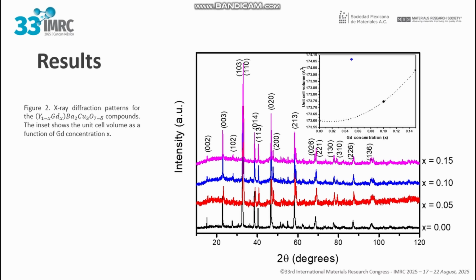These are the results we got. First, these are the diffraction patterns for all the compounds and concentrations. As you can see here, the compounds did not show too many chemical impurities. We got pretty much the phase that we wanted to get. And in the inset, you can see that the unit cell volume actually grew with the increase of gadolinium content in its structure, with the exception of 0.05. This volume was calculated using the cell parameters found by doing a Rietveld refinement.